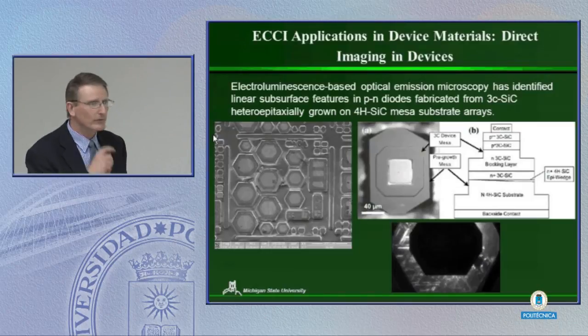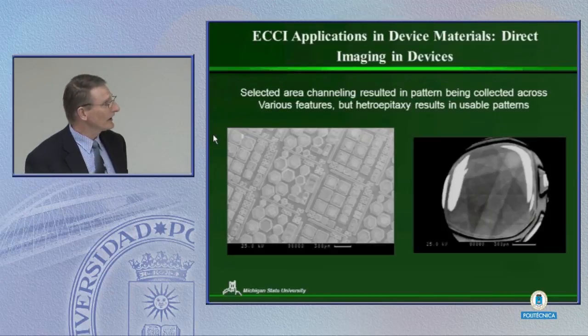And this is the work with Peruse and Kevin Spear at Case Western, where they brought me this chip and they said, well, they've done some thermal imaging on this, and they see these lines and they think they're dislocations. And they said, can we see if these are really dislocations? And I said, well, we can see if we have lines that image like dislocations, and do they look that way? And at first blush, we thought this would be quite a challenge because it's a little bit hard to get an orientation from something like this, or so we thought.